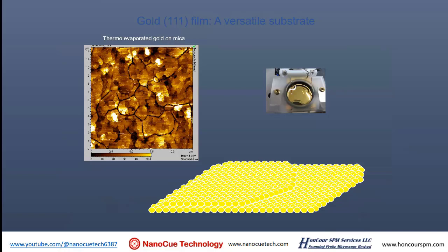Here's another very interesting substrate that people use in AFM imaging, which is gold 111 film, gold film. The reason people use gold film is that you can clean it in a very different way compared to HOPG and graphite. And also, the gold surface has very rich chemistry. You can grow something on the surface of gold much more easily using thiol chemistry, and then use thiol chemistry again to modify the terminal functional group. So you can modify the surface of the sample and achieve any kind of functional group you want.